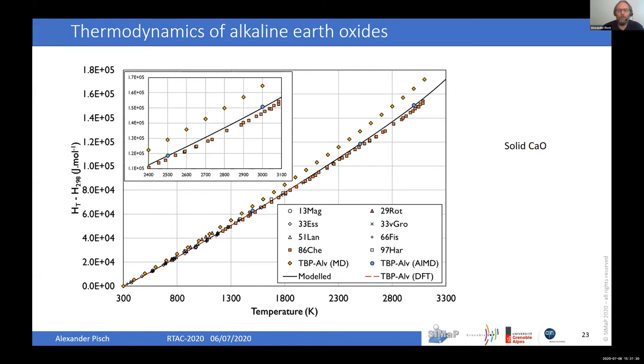And what about higher temperature? You see here these blue dots, and these blue dots are calculated by ab initio DFT calculations. So we used again the SCAN functional and do molecular dynamics calculation. It's clear that it's very, very time consuming, because you have a lot of atoms. In order to make it correctly, you have to have at least 300 to 400 atoms in the cell. Therefore, if you do a full ab initio calculation, it's not straightforward in terms of time. But it gives you excellent results. As you see, the three points are basically within the experimental uncertainty.